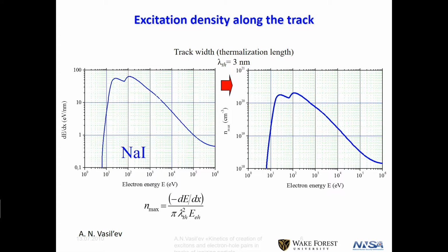But, okay, so first, what's going on in that track? And this probably from many fields you know this, and I came up through surface science for quite a while. And so I recognize this as one way of plotting the universal curve of electron mean-free path. So the mean-free path is not plotted here, but this is the dE/dx, eV per nanometer. Anyway, so here's the plot. At about 100 volts, every material, I don't care what it is, has a mean-free path of about 3 angstroms. And that's how come people can do surface science.